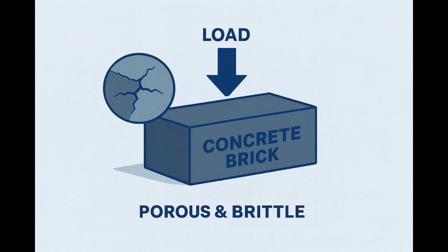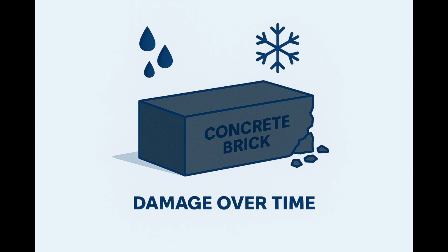Conventional cement bricks are our baseline. They use a cement matrix that is both porous and brittle. Under load, small micro cracks start to form inside the unit and grow as traffic and temperature cycles continue. When water enters and you add freeze-thaw cycles, the expansion of ice pushes those cracks further, leading to surface spalling, chipped edges, and ultimately replacement. This familiar degradation pattern is what EcoBrik is designed to improve on.